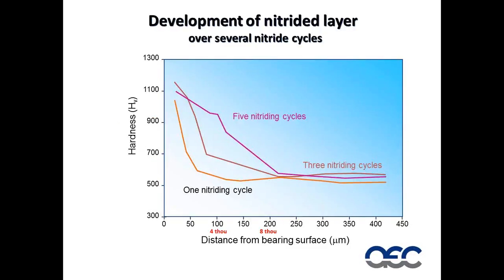Let us look at what we make. This is the hardness values measured going into the steel. And this first line here is the very first nitriding cycle. Note that as we increase to 3 cycles and 5 cycles of nitriding, the free nitrogen, which is in our steel here, can migrate both ways, and it goes inwards. So this nitrogen we have in here is going to be the nitrogen which gives us the good case depth after 3 or 5 cycles.